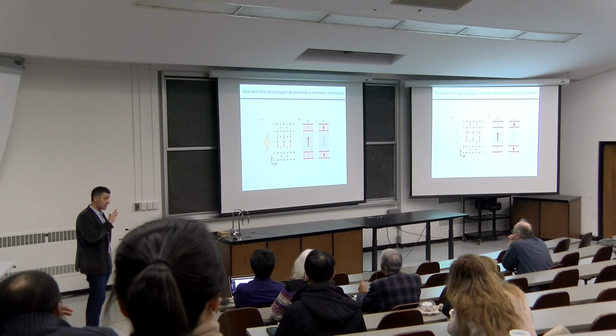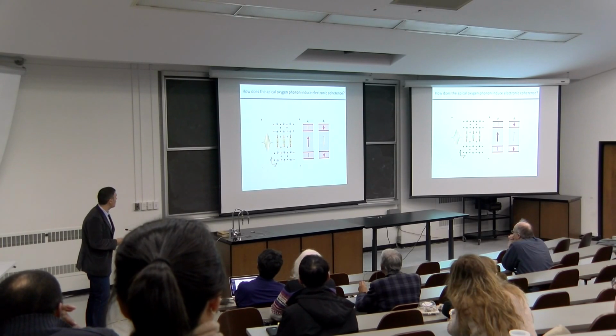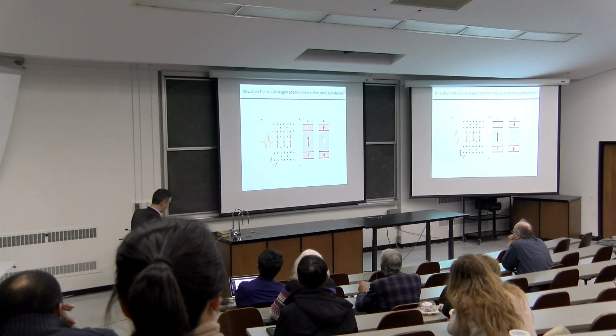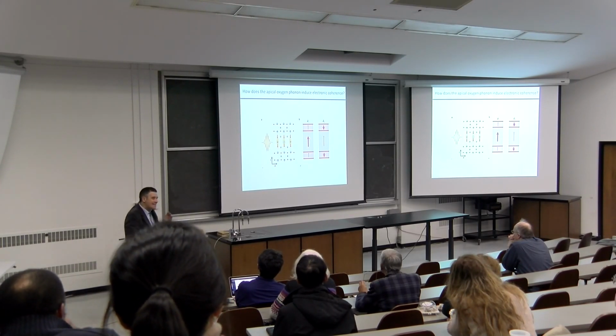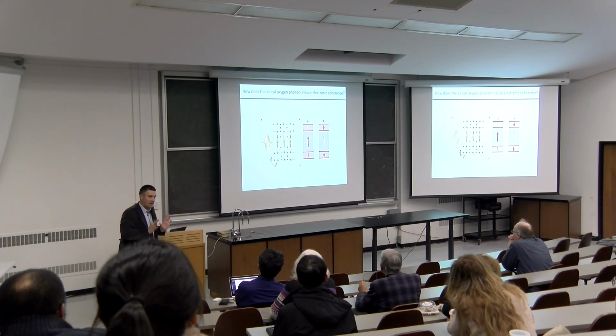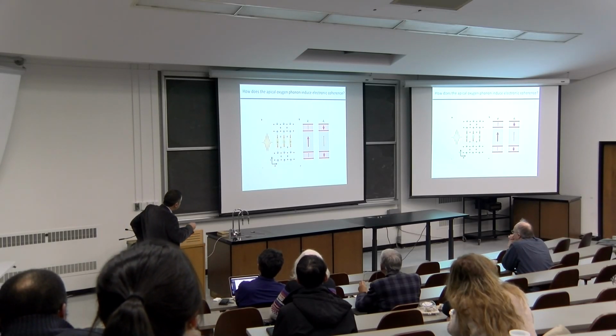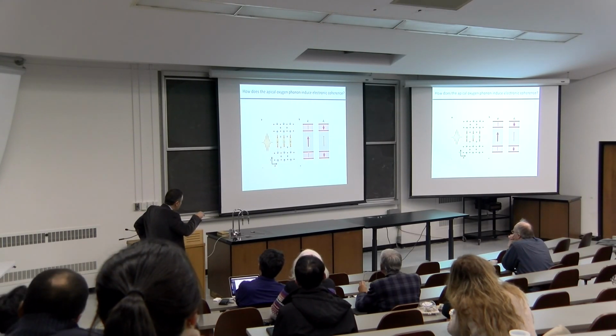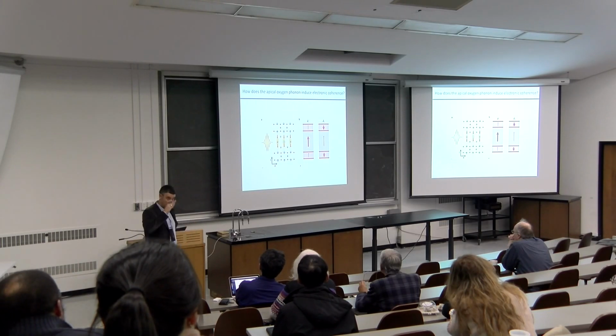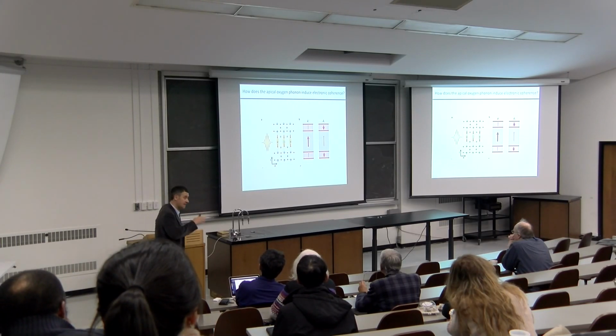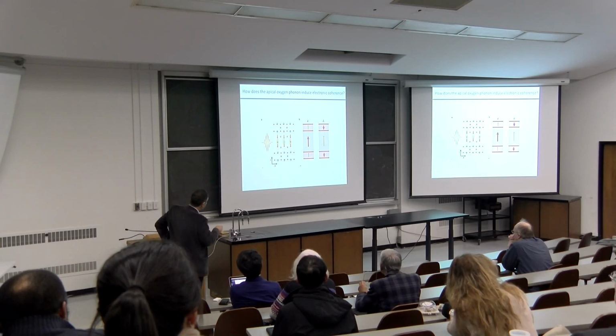Okay, but the problem that I want to discuss with you here, in the context of this nonlinear coupling between phonons and electronic orders, is one where I try to understand exactly what this apical oxygen phonon is doing, and how it is that by shaking this apical oxygen mode to large amplitudes, I'm coupling to these supercurrent tunneling modes between the planes. So I'm going to discuss the data below TC and then above TC.